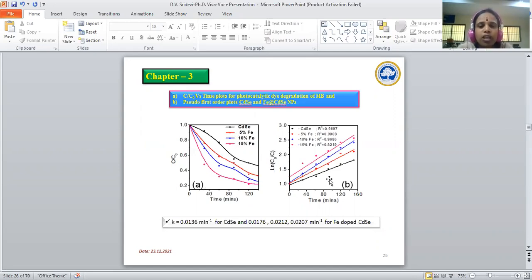Then figure B shows a kinetic plot of cadmium selenide and Fe doped cadmium selenide nanoparticles. The straight line degradation emphasizes that all the synthesized nanoparticles exhibit pseudo first order kinetics. The rate constant values for cadmium selenide is found to be 0.0136 minute power of -1 and 0.0176, 0.0212, 0.0207 minute power of -1 for 5, 10, and 15% of Fe doped cadmium selenide nanoparticles.